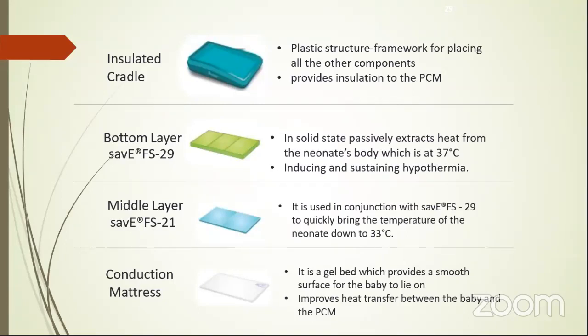Then the middle layer is used in conjunction with the SAVE FS29 PCM to quickly bring the temperature of the neonate down to 33 degrees Celsius. So the bottom layer is at 37 degrees Celsius, and this middle layer brings it to 33 degrees Celsius. And the conduction matrix is at the top, where we place our babies. It's a gel bed, which provides a smooth surface for the baby to lie on. That improves the heat transfer between the baby and the PCM. The conduction matrix only transfers the heat from baby to the PCM, and we have to keep a constant temperature without the baby getting any sores on the body. Otherwise the baby will face another kind of problem because of the sores.